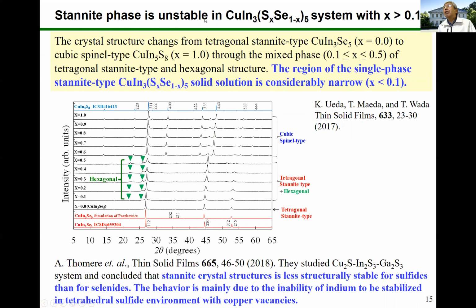The stannite phase is unstable in the CuIn3(S,Se)5 system. The crystal structure changed from tetragonal stannite type CuIn3Se5 to cubic spinel type CuIn5S8 through the mixed phase. The region of single phase stannite type CuIn3(S,Se)5 solid solution is considerably narrow. The behavior is mainly due to the inability of indium to be stabilized in a tetrahedral sulfide environment with copper vacancy.